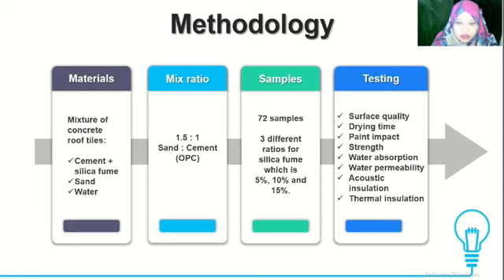For this research, concrete roof tiles are made of a mixture of sand, cement plus silica fume, and also water, which are molded under heat and high pressure. The mixing ratio used in this research is 1.5 to 1, which is sand and ordinary Portland cement, OPC. There are 72 samples produced with 3 different ratios of silica fume, which are 5%, 10%, and 15%.